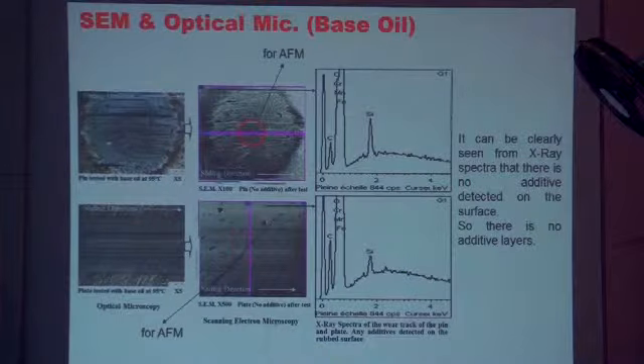Well, this is the test with base oil, so you see no additives on the surface. We carried out some tests by AFM here, and this is optical microscopy, but no additives here - this is carried out with base oil.